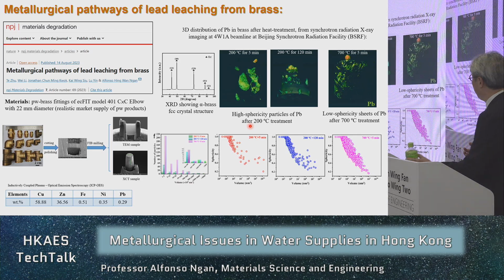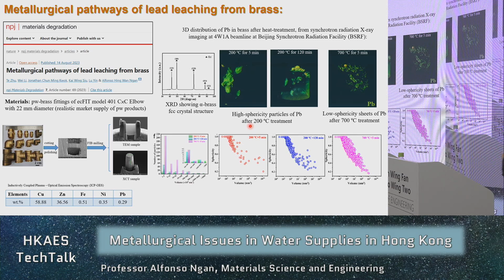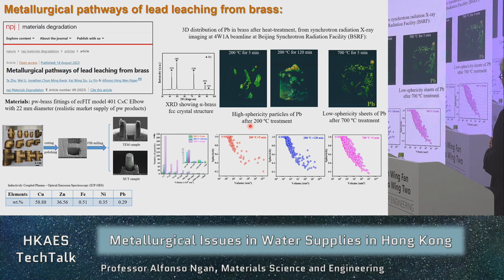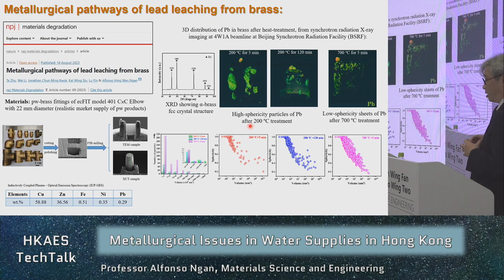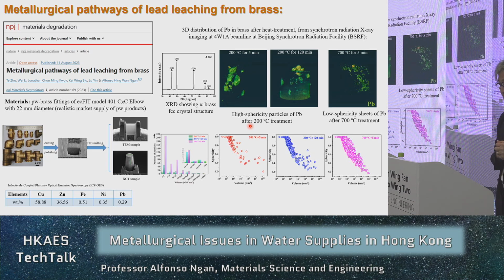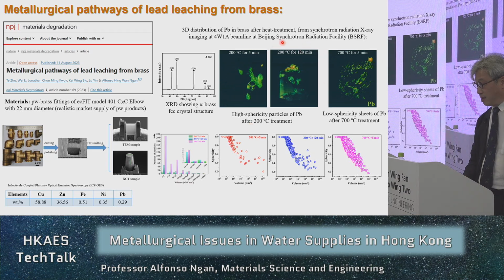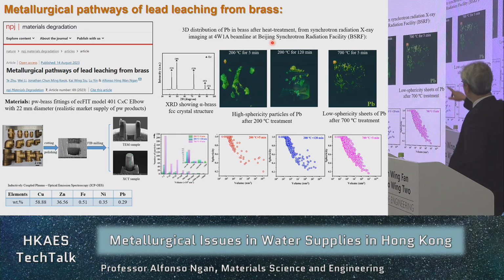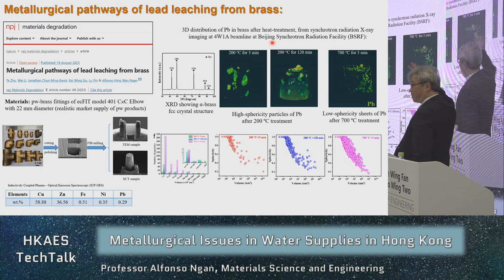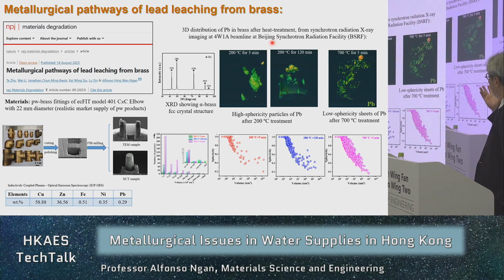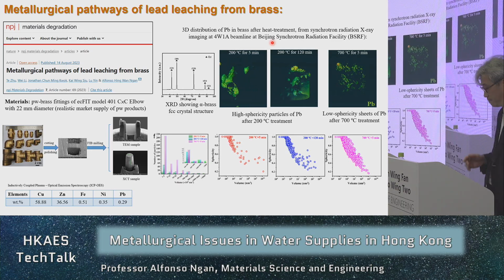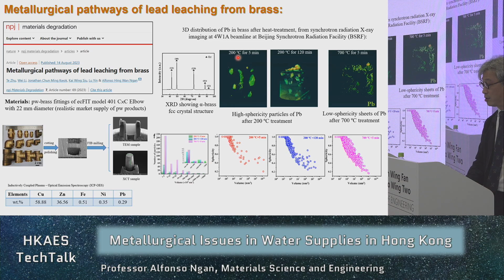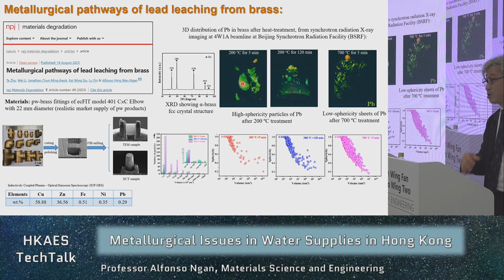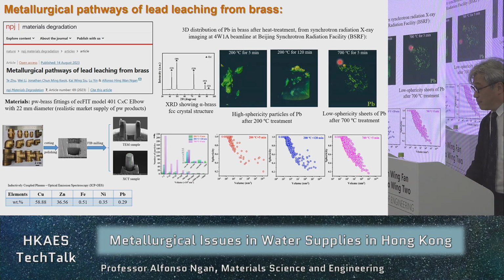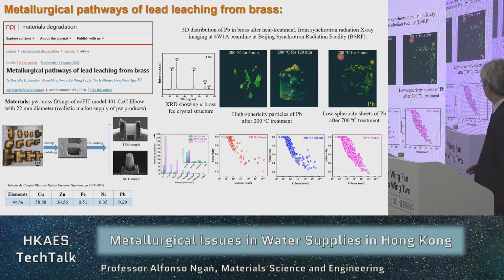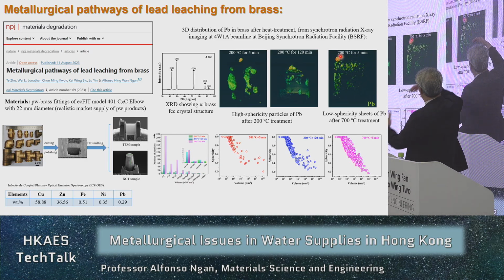So now we know that lead will come out, especially if you heat or cut or polish the material. But we also wanted to know the pathways. As I said before, lead is completely immiscible in copper, right? So we subjected some of these pieces to X-ray using the synchrotron facility in Beijing. The blue stuff is the lead. The black is the copper matrix, right? You can see that the lead is present in terms of particles, but if you heat the metal at a lower temperature, 200 degrees Celsius, the particles are more spherical, more rounded. But if you heat up at 700 degrees Celsius, the brazing temperature, the particles become more sheet-like, right?